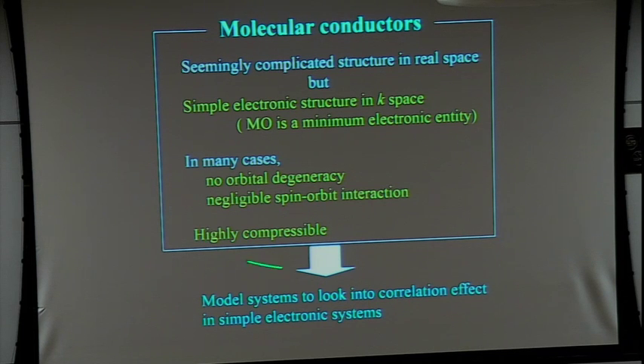An additional important point is the highly compressible nature, so you can easily control the material parameters by applying pressure. Roughly speaking, the pressure effect is 10 times larger than in inorganic materials.